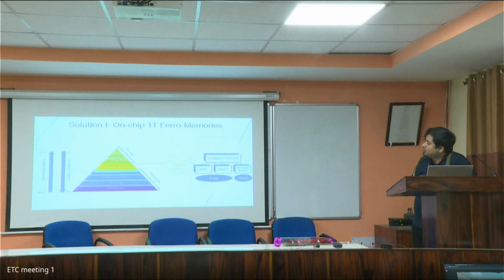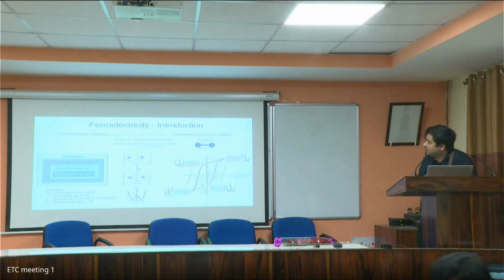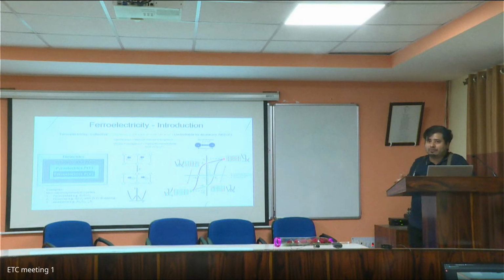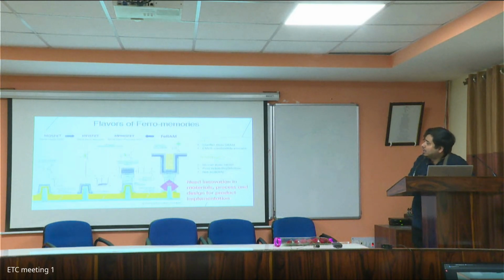For cache, we usually use SRAM, which has been the dominant force. But there are some alternative solutions that have been under research. One of them is the on-chip ferroelectric memories. Ferroelectric is this particular material in which you can switch the dipoles in different directions, and it can retain that particular state. So you can get a 1 or 0 depending on which state you have flipped your dipoles to. So you can take these ferroelectric materials and put them in whatever way you want on a transistor, and you will get these different flavors of memories.